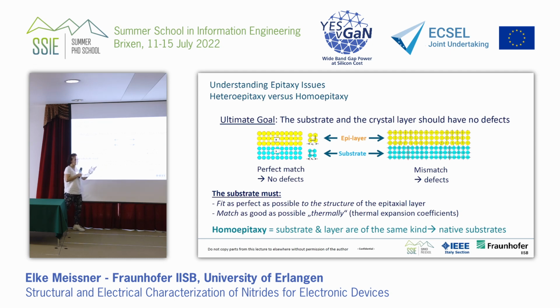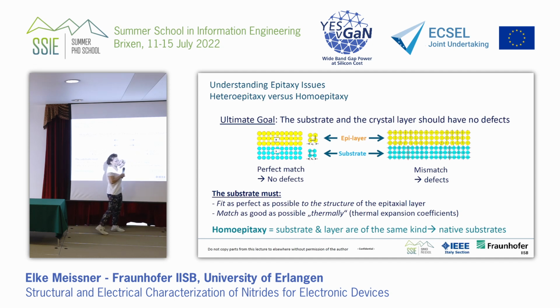But this is what we don't have in the gallium nitride on silicon case, for example. So we have a substrate of one kind and the epi layer of another kind. And now you have mismatch, in two respects. So we have thermal mismatch. If we cool something and heat something, which is the epitaxial process, so it has some temperature profile, then these materials will work against each other. So thermal expansion is different.